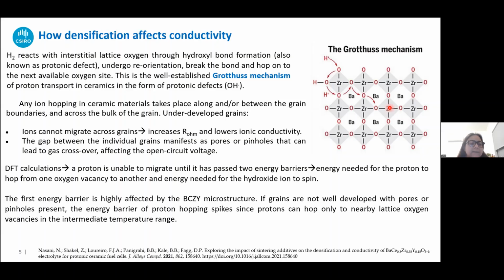And also in a recent study, it was shown through DFT calculations that whenever a proton is migrating, there are two activation energy barriers. So one is where the proton needs to hop from one oxygen vacancy to another. And the second activation barrier is basically the energy needed for the hydroxide ion to spin. Now, the first activation barrier is highly affected by the BCZY microstructure. So that's where the density and the grain size, the grain growth, how well developed they are, these things matter. So if the grains are not sufficiently developed, if they are not overlapping each other, then the energy barrier for the proton hopping is very high, and eventually that leads to a drop in the ionic conductivity of the material.